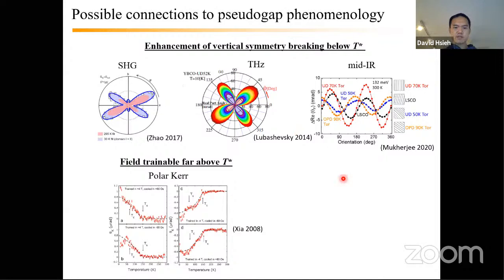The polar Kerr effect that was reported back in 2008 on YBCO also shows this interesting phenomenon where you can field train the sign of the signal far above T star. So if you go far above T star and you slap on either an up or down oriented magnetic field of order 4 Tesla, you can actually switch the sign of the Kerr trace. And so that points towards some ordering already set in far above T star, which is a bit reminiscent of what we see as far as the inability to flip our domain, even thermally cycling above T_N in SCOC.